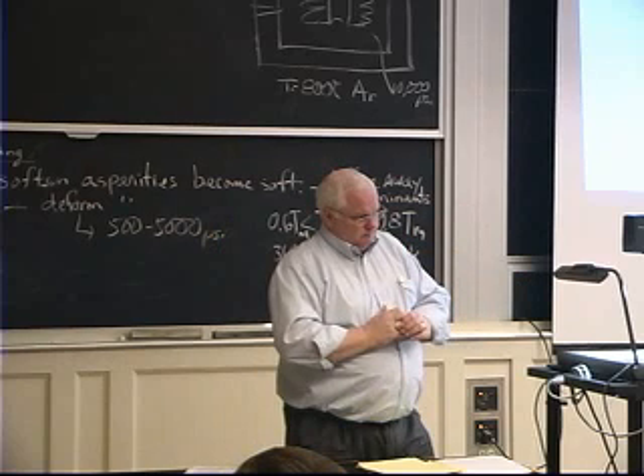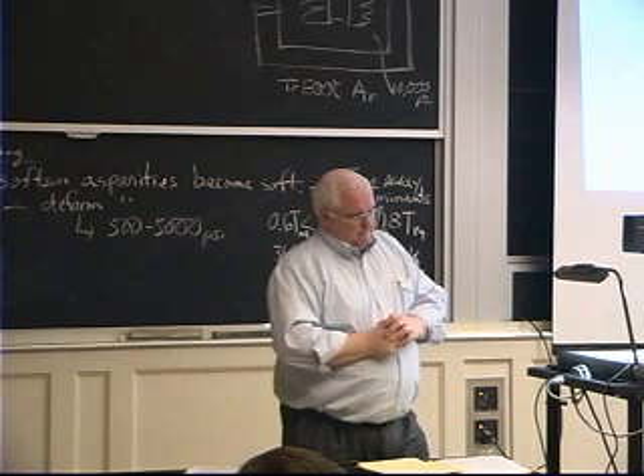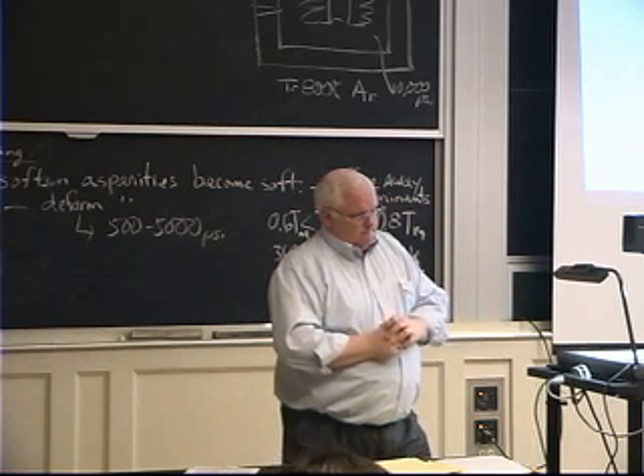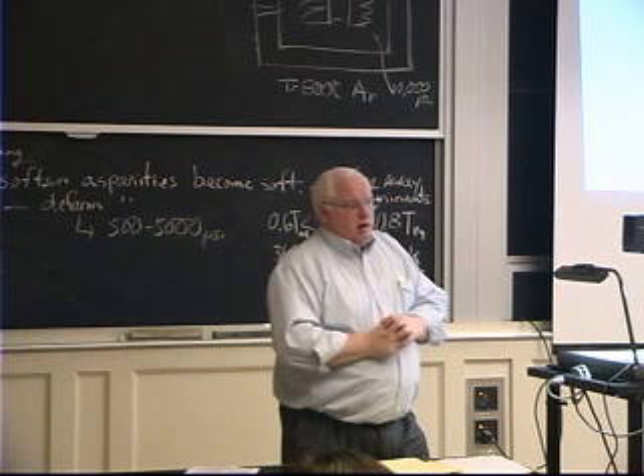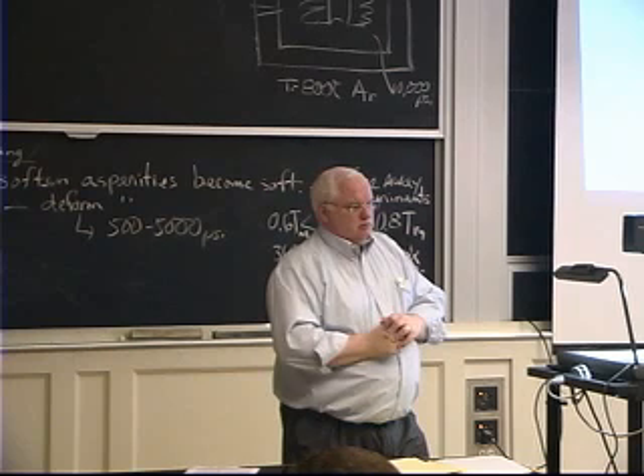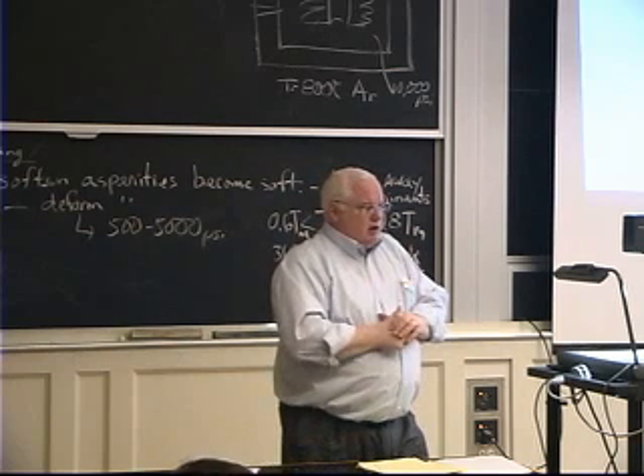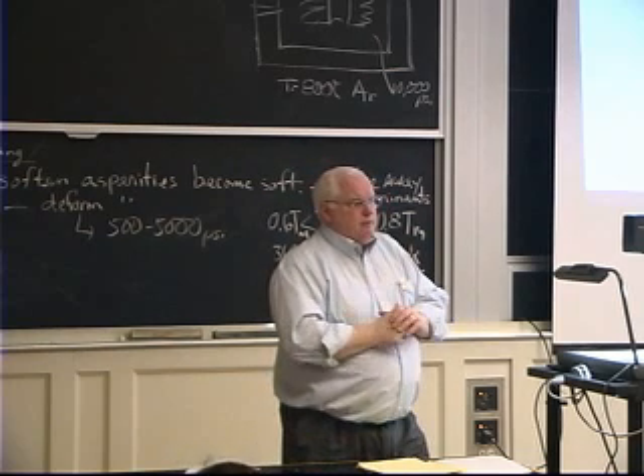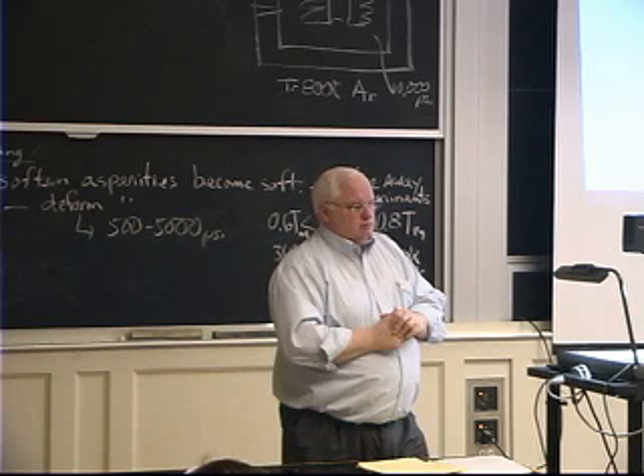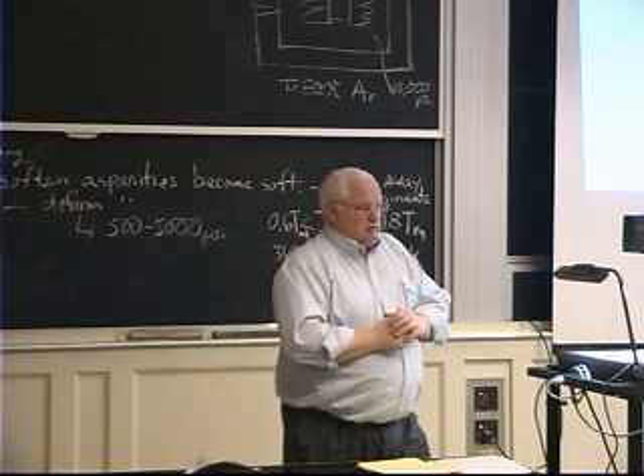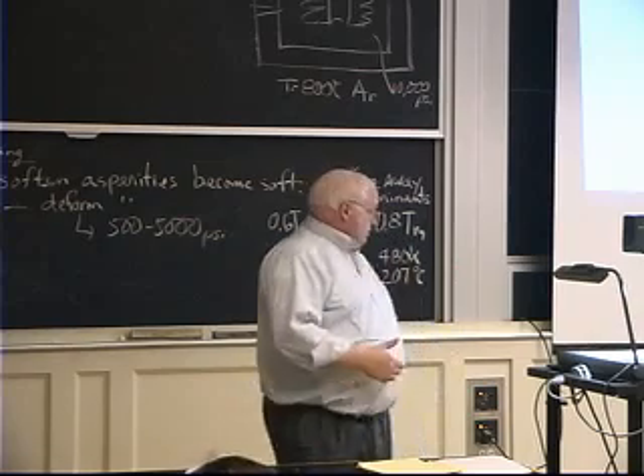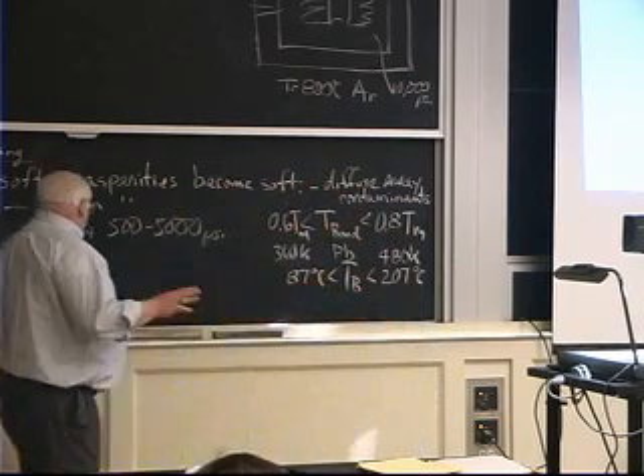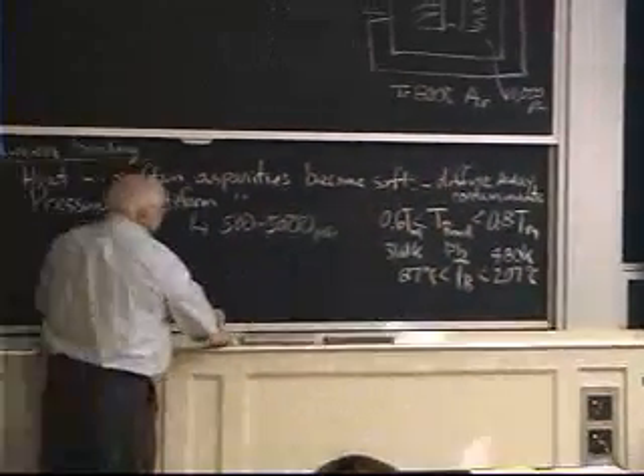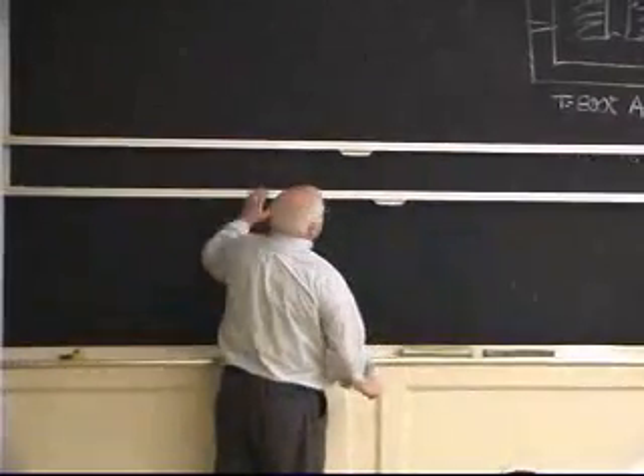Just to understand the bigger picture, I guess, the diffusion bonding, the bond that it makes, is it just as strong as, say, a weld bond? A well-made diffusion bond is a near perfect weld. In something like titanium, you will not microscopically be able to find the joint. It is indistinguishable from the surrounding material, in the right material. So it is better than a fusion weld. It's a near perfect joint. It's as close as we come to a perfect joint.